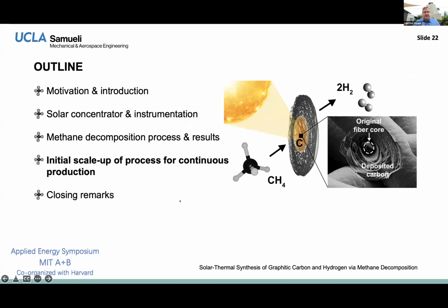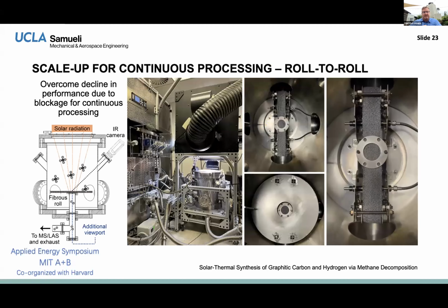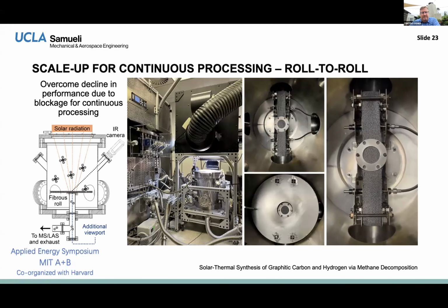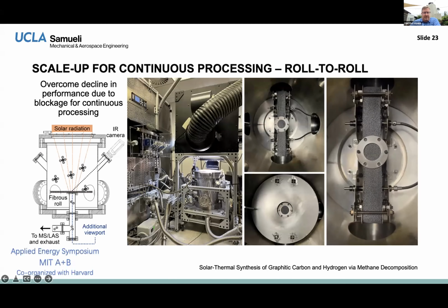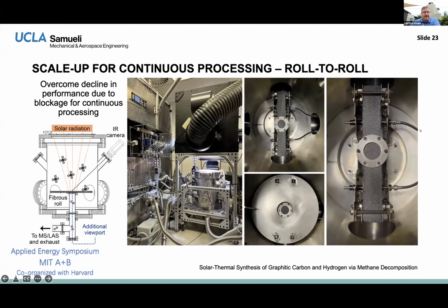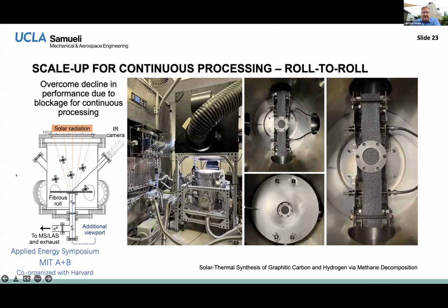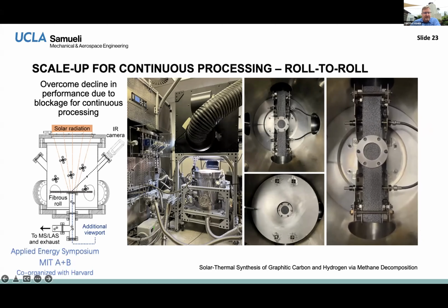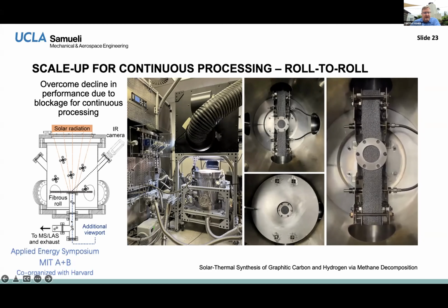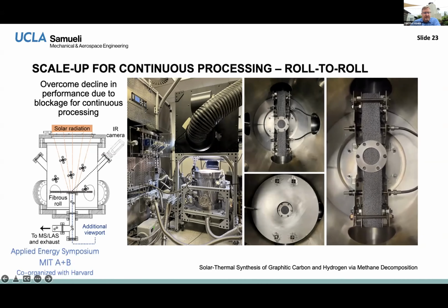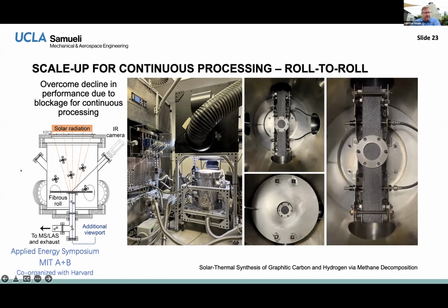The reason is that we can easily do this process in a roll-to-roll manner. We've done it before with plasma CVD. So what Mostafa did was he built a roll-to-roll system. You can actually see it moving here. It doesn't go that fast. Well, it can go faster than this, but it's actually moving on your screen right now. This is just our initial attempt at it. It's done in a different reactor, so we had to change things up in terms of diagnostics. But we have the infrared camera pointed this way. We do have a viewport where we have a spectrometer that can measure temperature from the bottom.